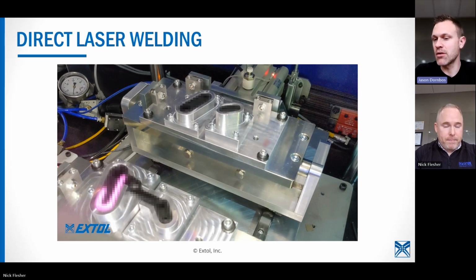Okay, so can you address the smoke? I should have done that proactively. Okay, so this is the case where smoke shows up in laser welding and would be for any IR welding. It was a single laser on this particular one. Smoke in laser plastic welding, especially with black nylon parts, is oxidation that's happening. You're essentially just burning the part, and it happens without really much control. We evacuate it. In this case, this was actually in the prototype machine. We did do a production machine, and we evacuated it really, really quickly.